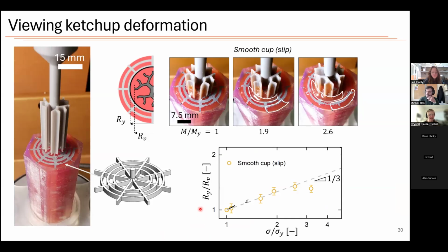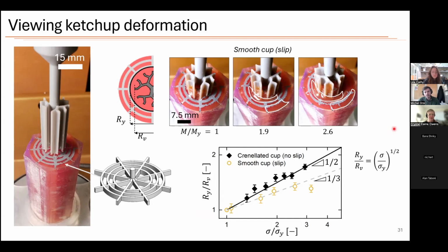Here we can plot the yield radius over the vane radius as a function of the applied stress. And we find when we have slip, it falls below what we would have expected from the 1/2 power law. And if we do the same test in a cup that has texture, then we find it obeys what we would have expected. So this confirms that when the material slips, not all the energy is going into shearing the material. There's a lot that's lost to the material just sliding along the surface.